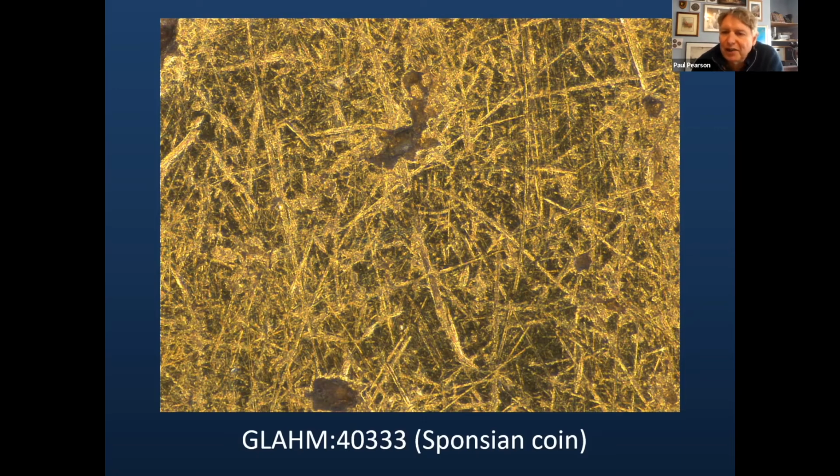Again, we have to turn to our colleague Jacek Olenda, who did a lot of this more detailed analysis. We compared this pattern, which you can see is covered in scratches, with genuine Roman coins that we know were in circulation, and in all respects it looks similar. It would be impossible for me to tell you which coin these come from, because you get scratches in all orientations. They overlap, there are many of them, and under the electron microscope they go down to the very tiniest length and width scale you can see. So in all respects the wear pattern looks like a genuine wear pattern. But we do know that sophisticated forgers had various methods for aging their coins, so that's not in itself proof of authenticity.